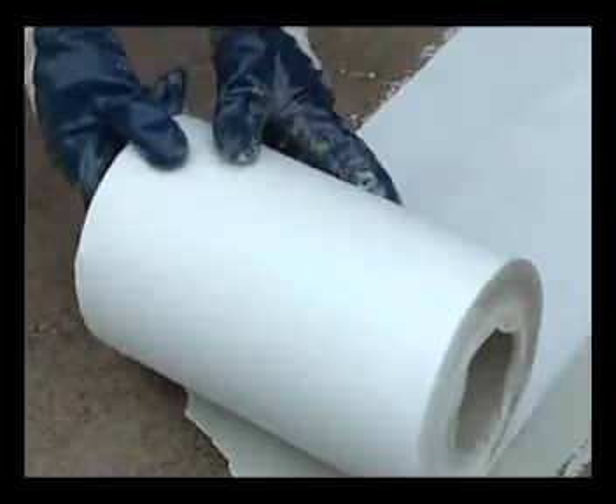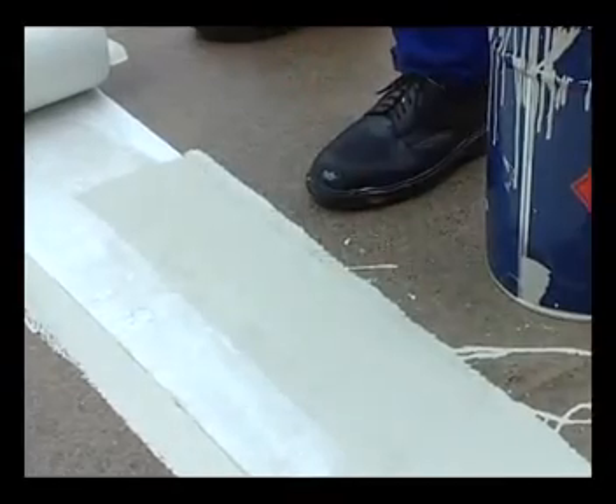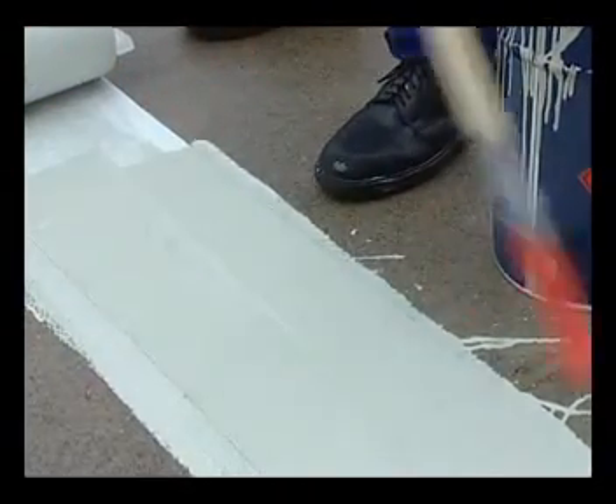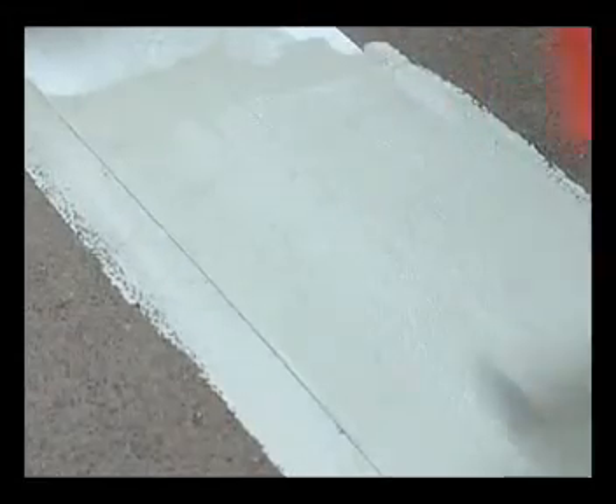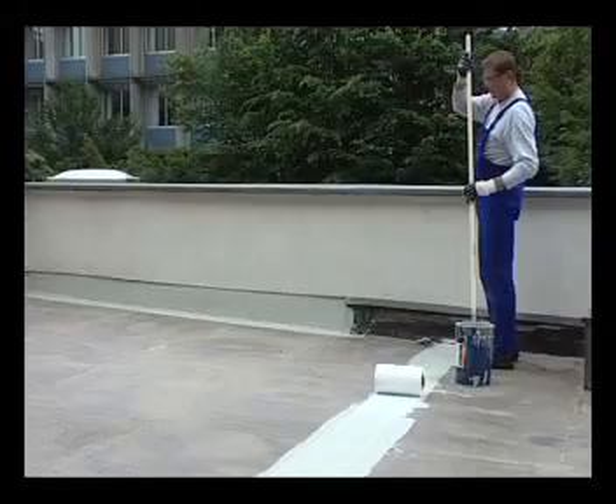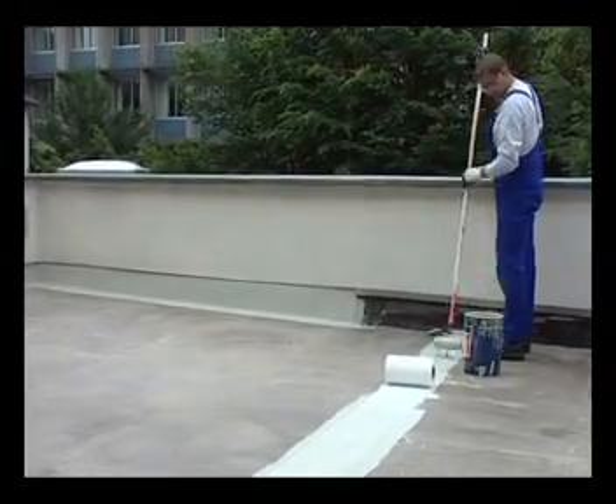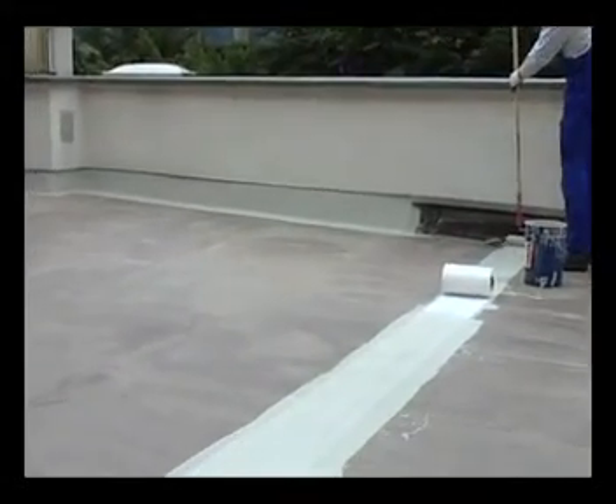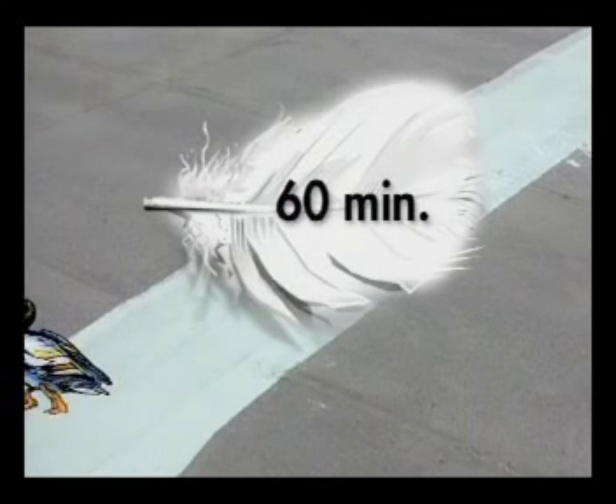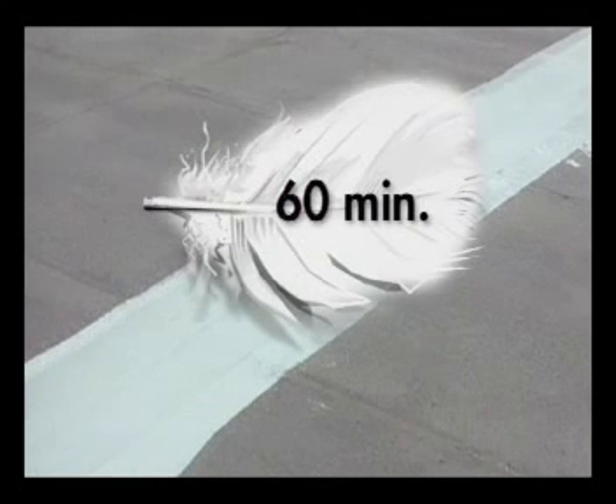Wrinkles and creases should be rolled out. Then apply the KEMPEROL AC resin with the purlon roller until the fleece is completely saturated. The quantity ratio for initial and subsequent application is 2/3 and 1/3. Thoroughly smooth out air bubbles from the fleece. The treated surface is rainproof and can be walked on after 60 minutes. Treatment can continue after only an hour.